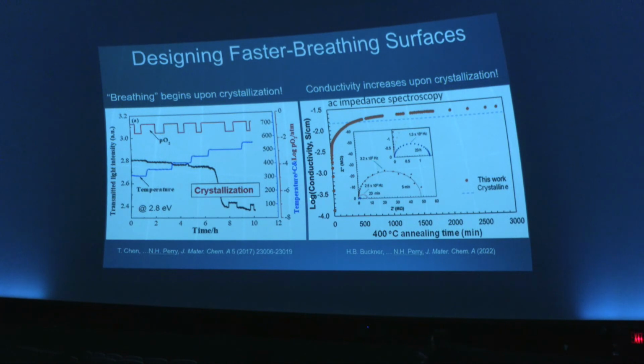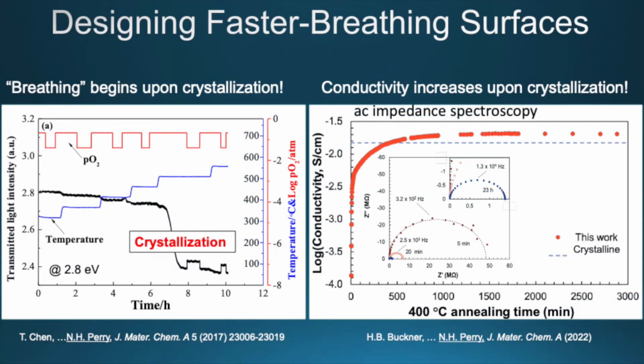The other thing that we did was we can measure the electrical conductivity of these materials in that same time frame. And what we saw is that they start pretty low, but they shoot up as we crystallize them, as we transform them. And so these materials are all of a sudden able to move electronic charge through them really quickly when this transformation happens. And so this is different from what's going on at the surface, but it's another reason for why they start to behave so well and they start to breathe really well. It's because this charge can move through and help that surface reaction.